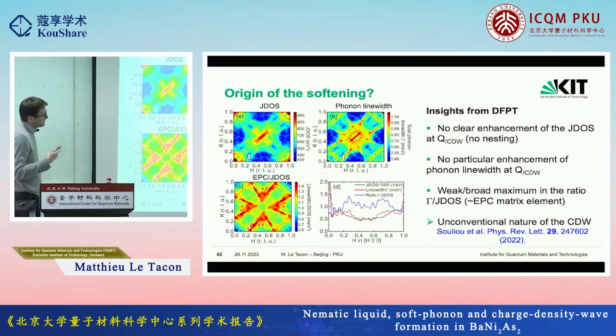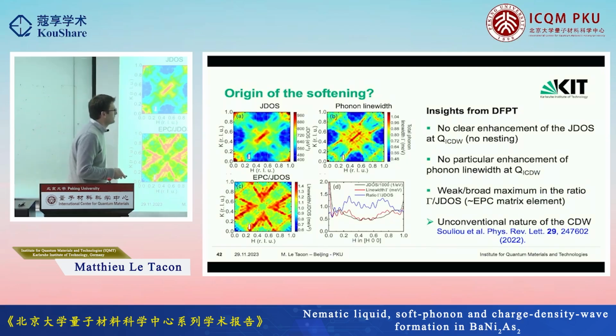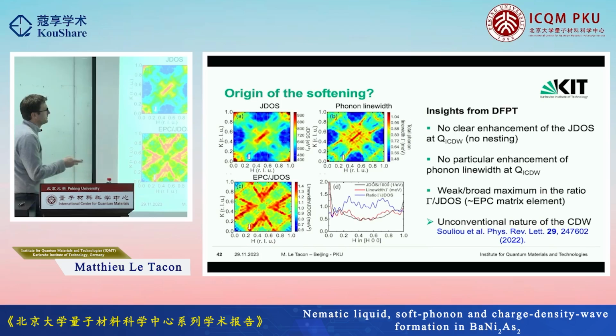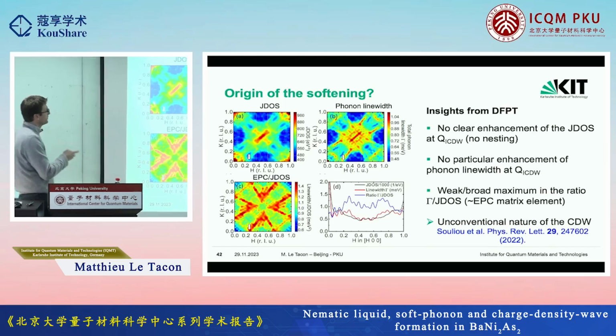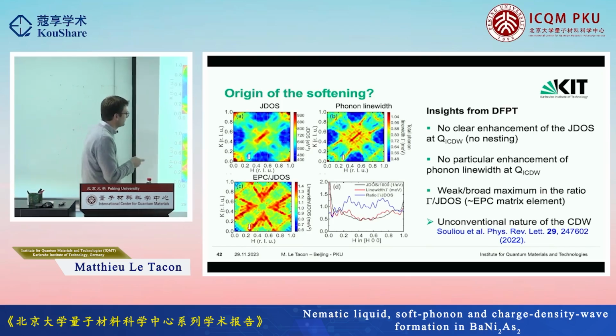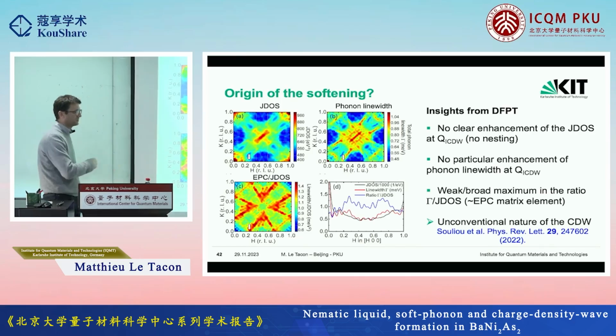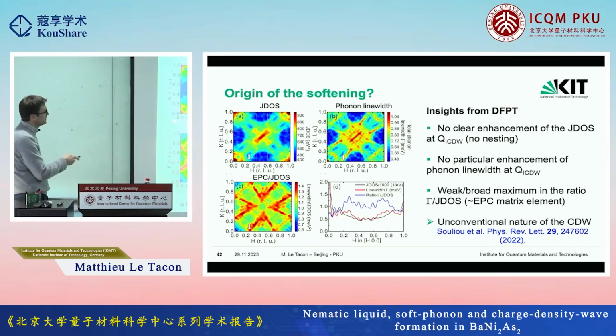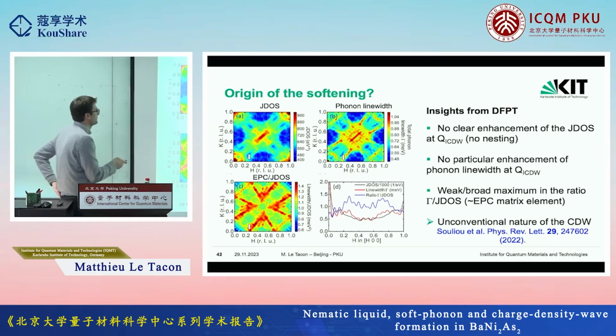Now, regarding the origin of the softening, well, we can get some insight again from the first principle calculation. And so the way to look at it is, we can look at the joint density of states of the system. So that's basically an indication of whether there is a Fermi surface nesting. And you can see that at the Q of the wave vector, at the Q of the incommensurability, there's pretty much no particular structure related to the Fermi surface of the material.